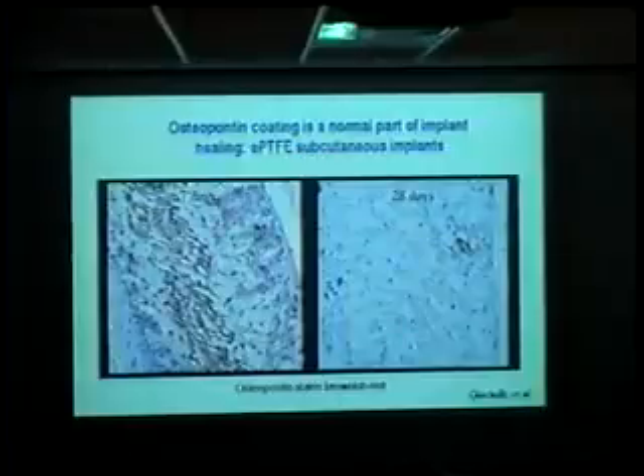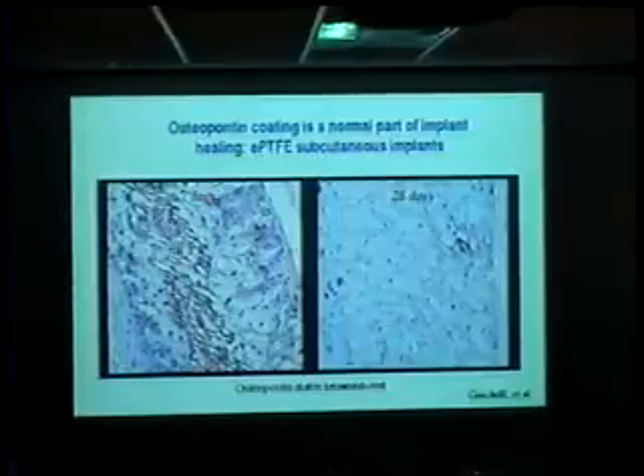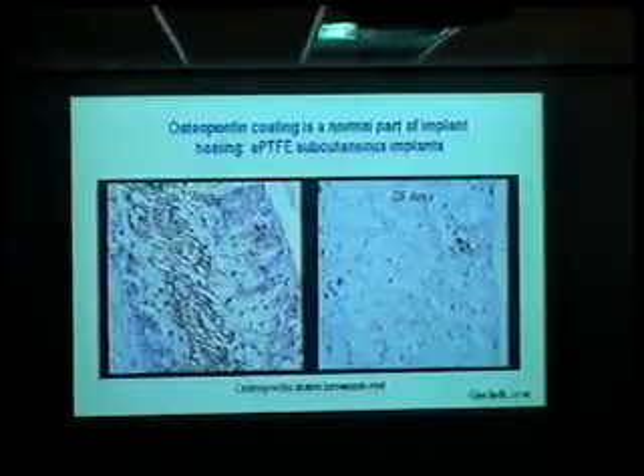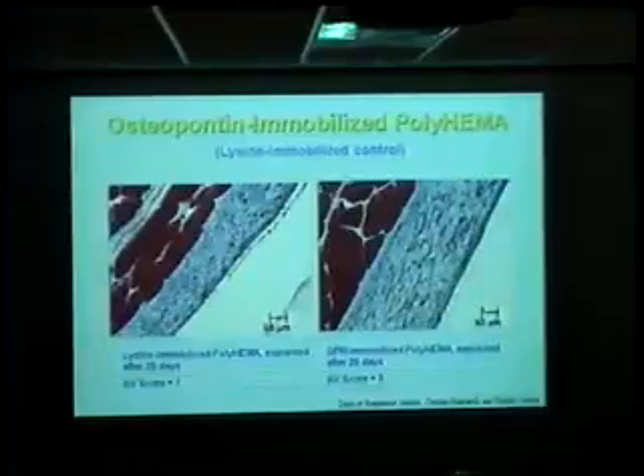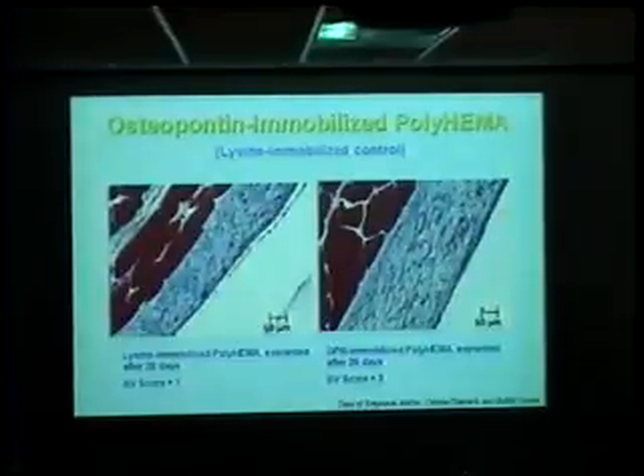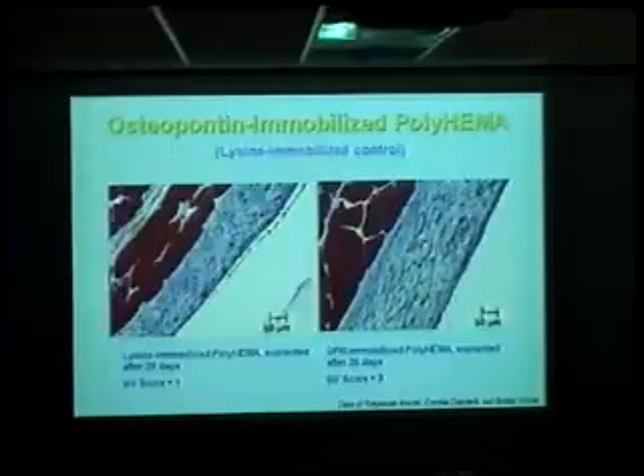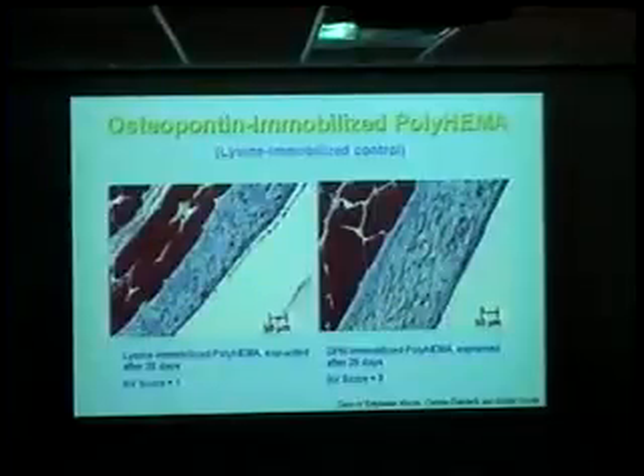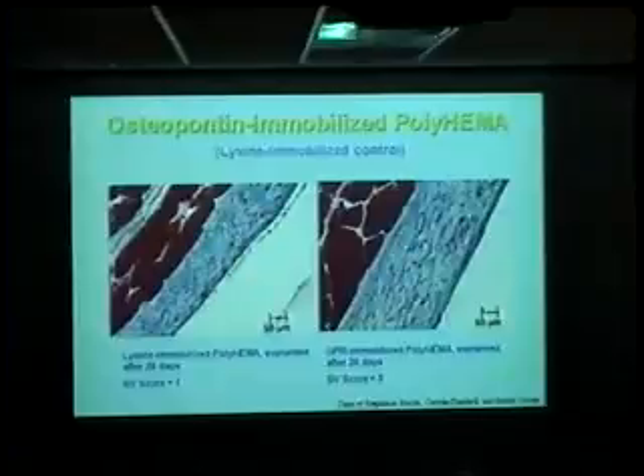This purple-brown color is a stain for osteopontin, one of these materials. And at 7 days, one sees considerable osteopontin in a healing piece of Teflon. At 28 days, it's essentially gone. The wound is healed. So they are present in healing. And in some recent experiments, what we've done, and this is our PhD student Stephanie Martin, has immobilized the osteopontin to the material, in this case polyhema, just sort of like a soft contact lens. And if the polyhema is implanted, and this actually has a lysine immobilized on the surface of polyhema, just to be an immobilization control for the osteopontin.